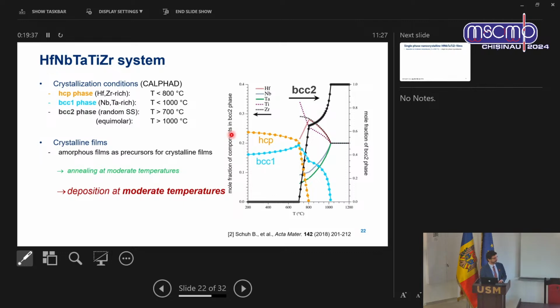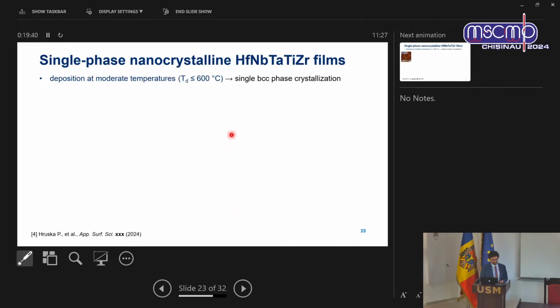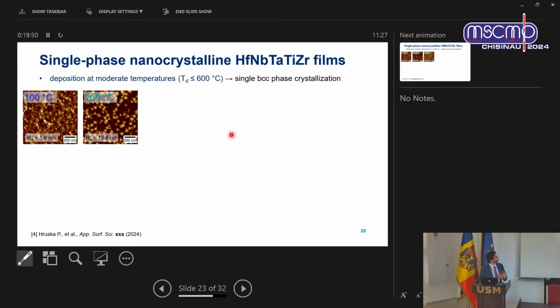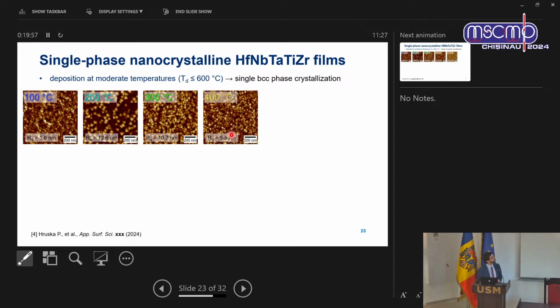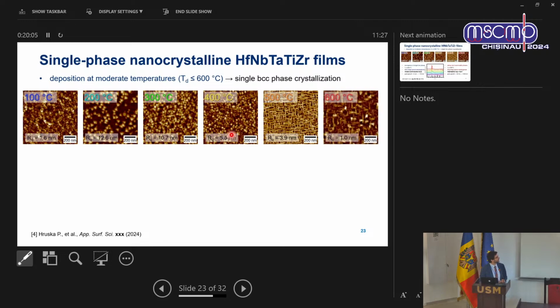If we increase the deposition temperature by 100 degrees, it is still amorphous, but at 200 degrees we started to observe crystallization. At higher temperatures, we have already a compact nanocrystalline film. Further increase goes to final crystallization of this fabric-like morphology. And when exceeding the temperature of 600 degrees, you can see that this 500 degree structure was metastable and it dissolves at higher temperatures, and this is actually the transition to the crystallization of those intermetallics.